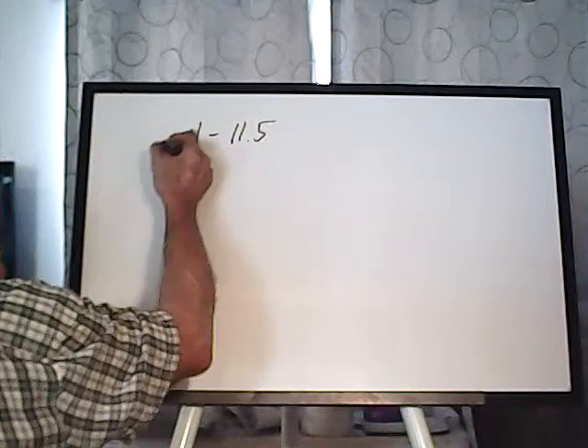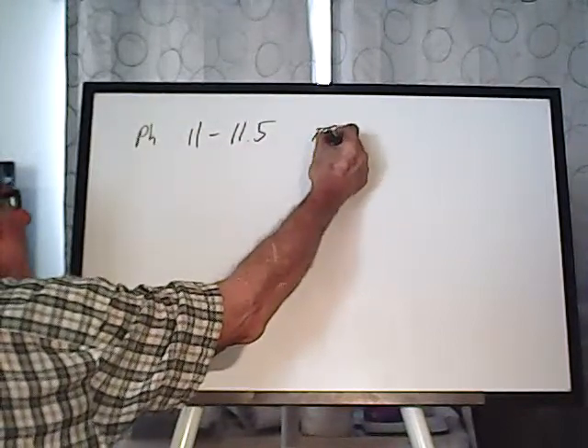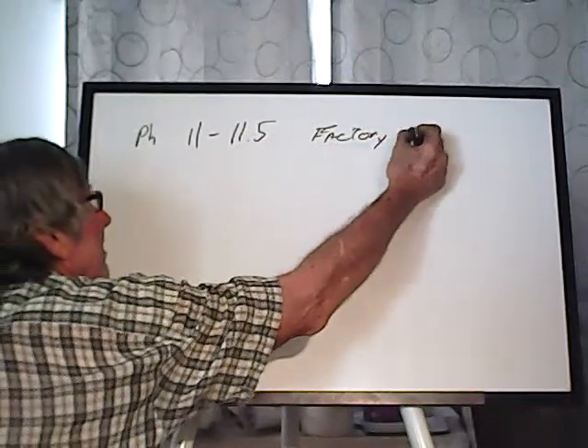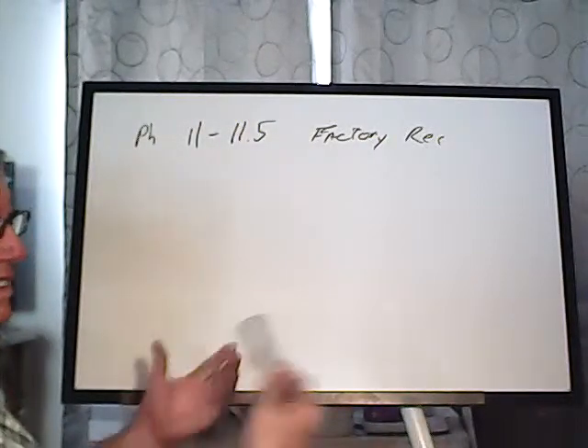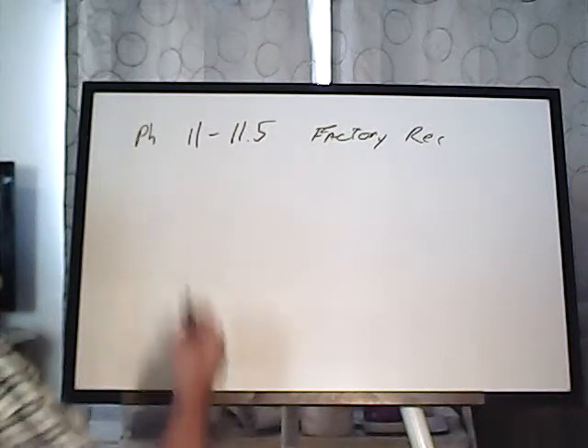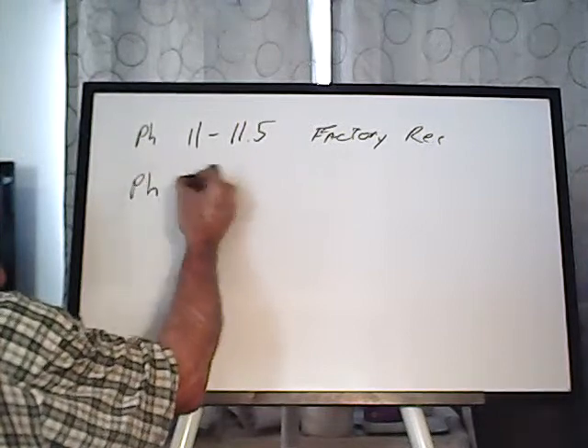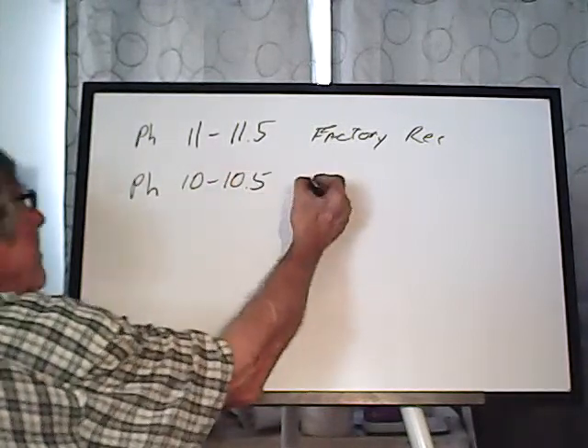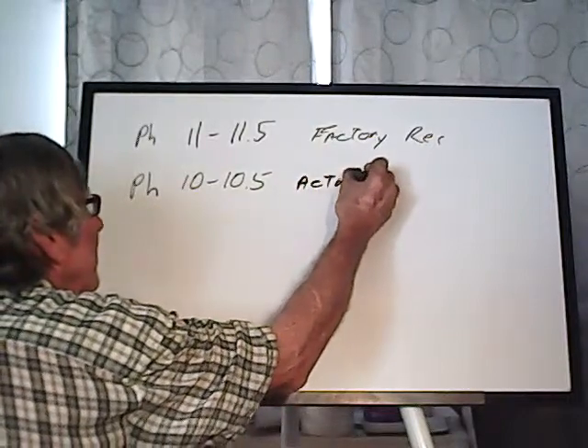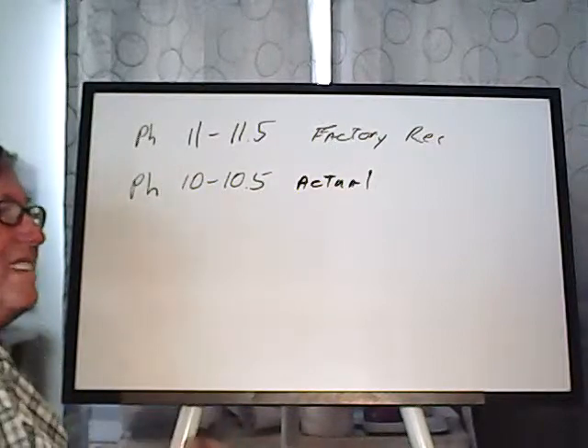So anyhow, we're getting the gold into solution from the ore just fine. That seems to be working well. The rolling bottle tests were quite good. It did seem that by reducing the pH, the factory pH was 11 to 11.5, the factory recommendation, this is what the manufacturer said we should use, this created a lot of secondary reactions to put a lot of other stuff into solution and actually kind of slowed things down. We found for practical purposes that a pH of 10 to 10.5 speeded up the dissolution and reduced those undesirable side reactions.